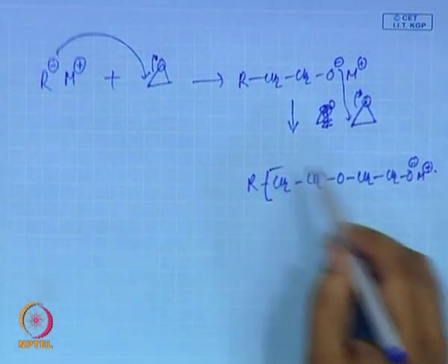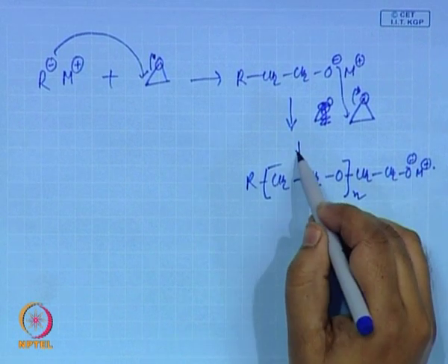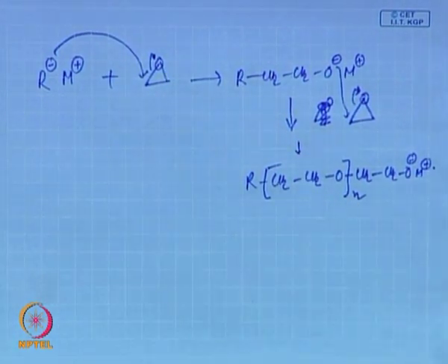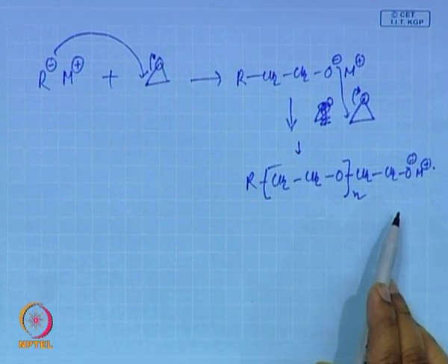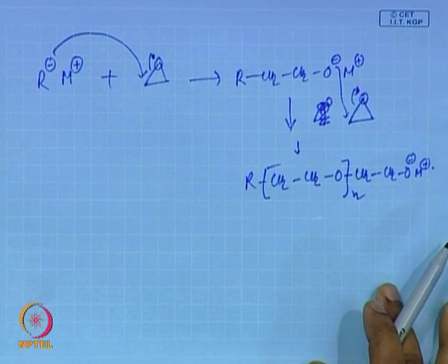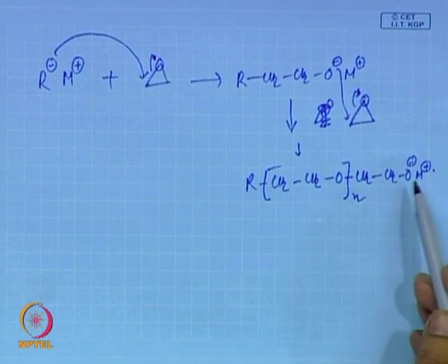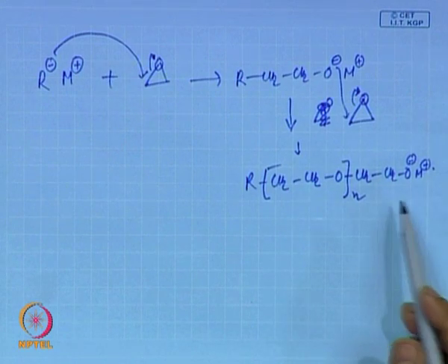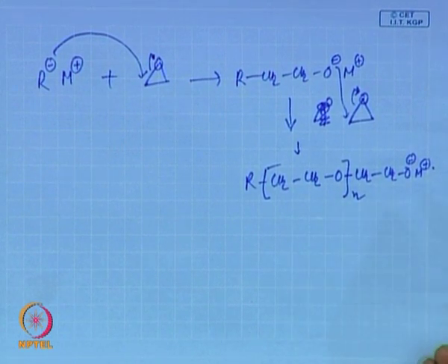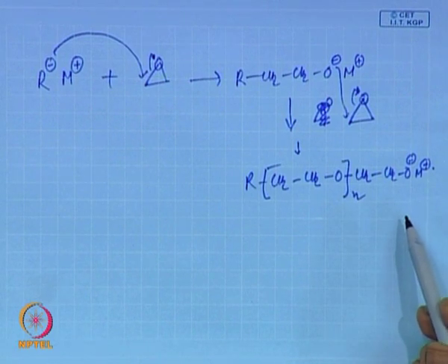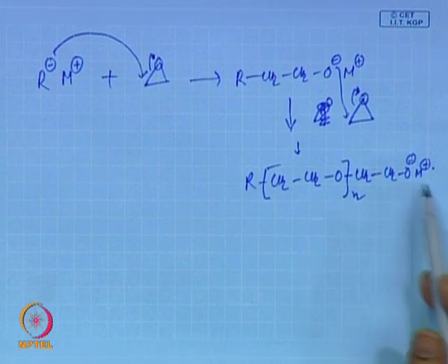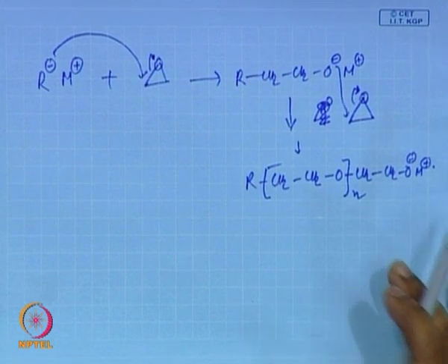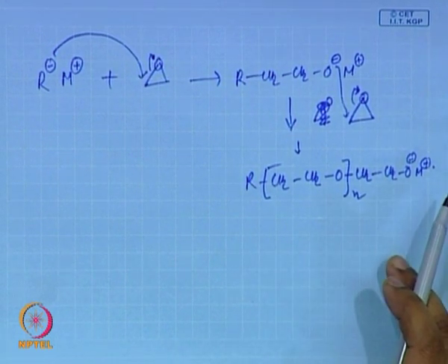So, in general, you can increase the number of steps and you will get your polymerization. Now, as I said, like other anionic polymerization, this is a living polymerization. So at the end of the reaction it remains like this, and you can add a second monomer and make a block copolymer. If you want to terminate the reaction, you can add some water or alcohol, and then you can exchange, like the other cases we discussed earlier.